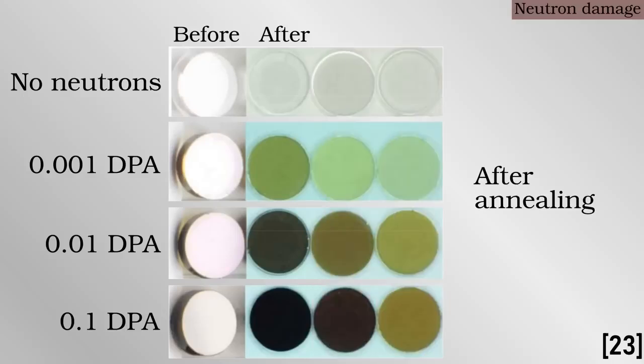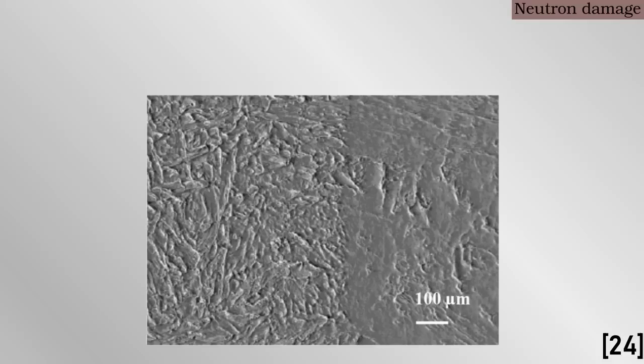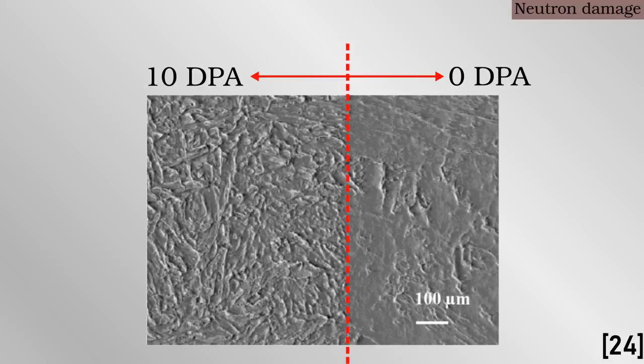On the bright side, the study also shows clear evidence that the damage can be repaired somewhat by annealing or heating the material. Indeed, this is something many other experiments have reproduced. The damage scales up with the number and energies of the neutrons. In many ways, this is uncharted territory for science. For the reasons I've mentioned, even fission plants do not reach these levels of neutrons. One particular concern is that microscopic gaps will open up in the material surface, trapping tritium among other substances.